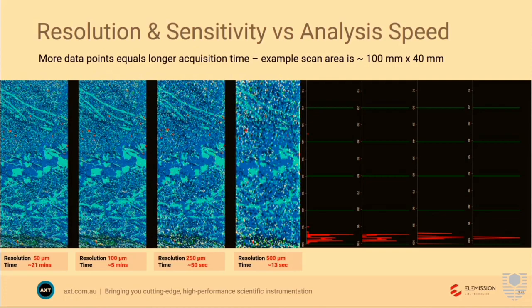So what does the data look like at lower resolution? This is a section of core, 100 mm by 40 mm. Analysing it at the highest resolution took 21 minutes. By spacing it out, the analysis time gets a little faster. So 100 microns is 5 minutes, 250 microns 50 seconds, 500 microns 13 seconds. But what does that do to the data?